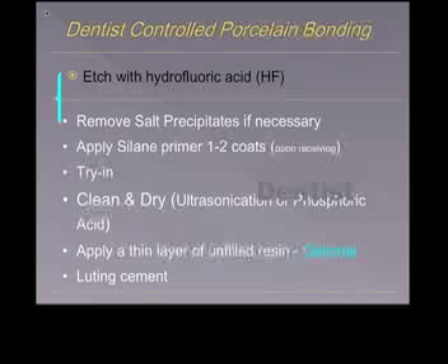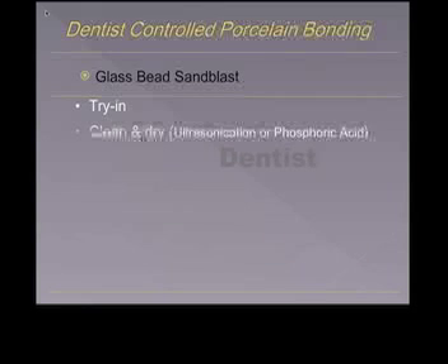So this method is the best since the dentist can control everything, but it's also more time-consuming for the dentist. BISCO's introduced this 9.5% hydrofluoric acid to reduce the etching time from 5 to 6 minutes to 90 seconds. So sandblasting with alumina is perhaps not a good idea.